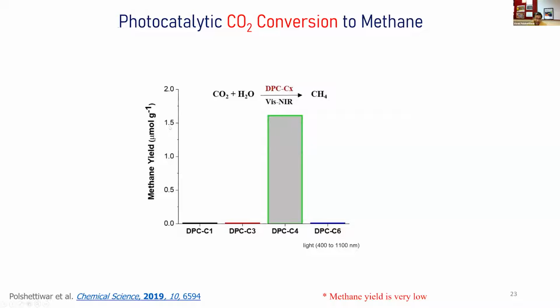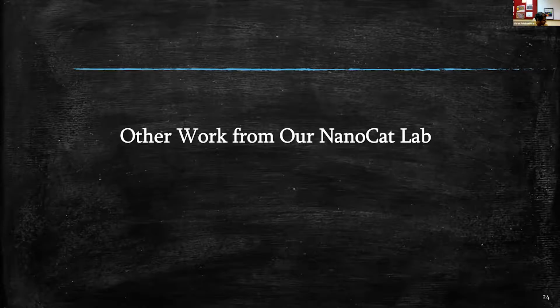Unfortunately, the yield as such is very low. 1.5 micromole is extremely low. So one has to really improve the yield, and this can be done by improving the lifetime of the material, the lifetime of the hot electrons, and that is something we're working on. I have another 2-3 minutes, so I will quickly touch upon the other work that we do